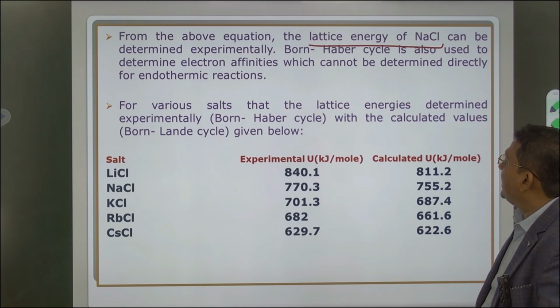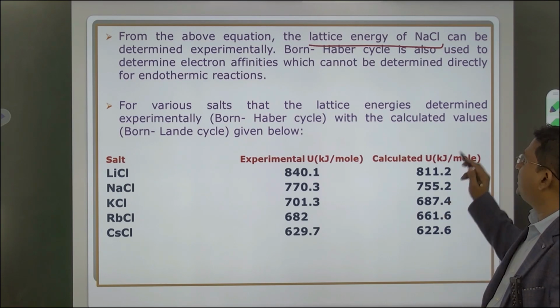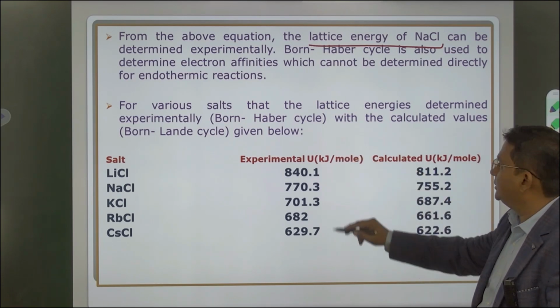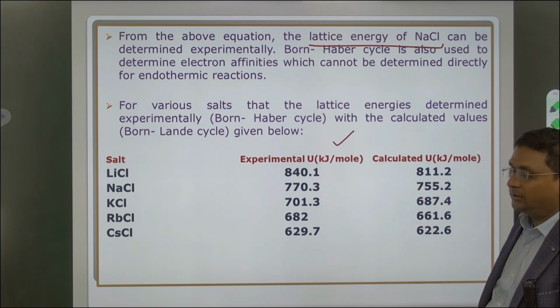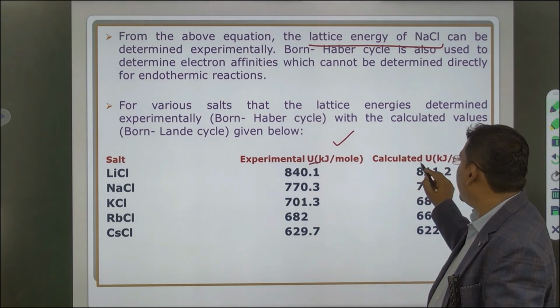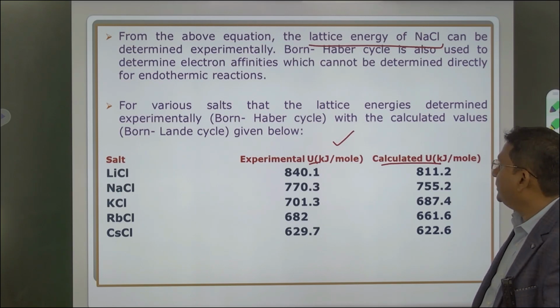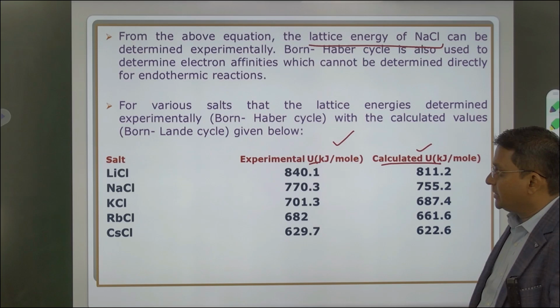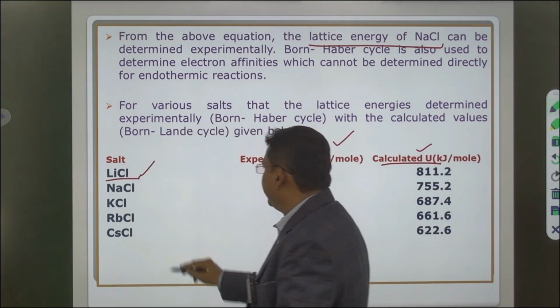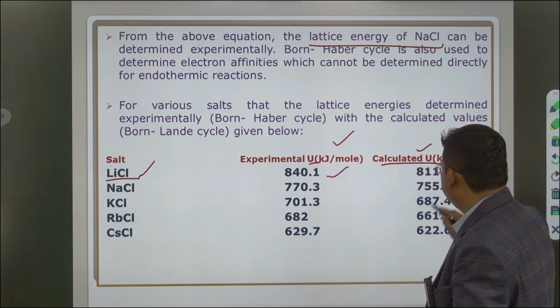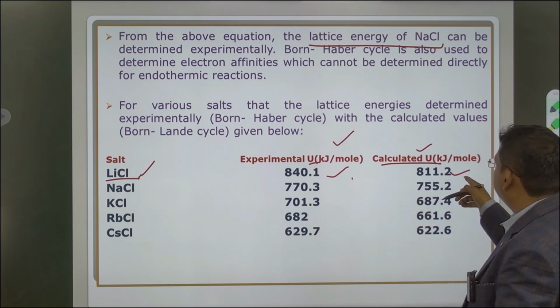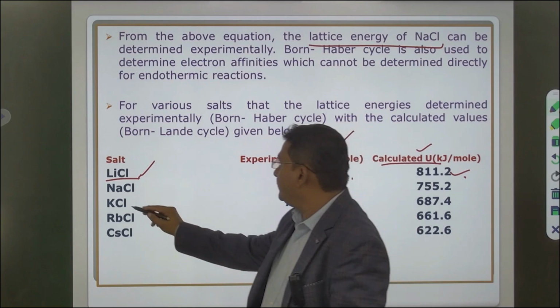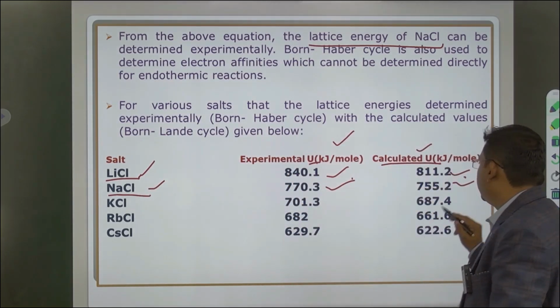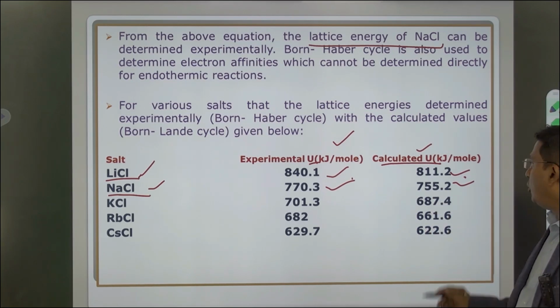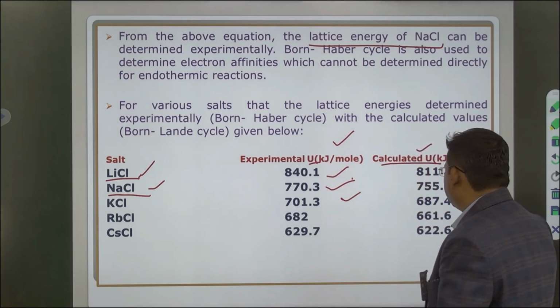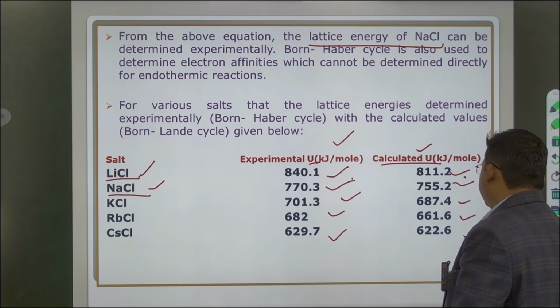For various salts, the lattice energy determined experimentally is compared with the value calculated from the Born-Lande cycle, given below. This is the experimental data of lattice energy, and this is the calculated data for the salts. See, lithium chloride: this is the experimental value and this is the calculated value. Like NaCl, we also find close values of experimental and calculated values, as we see here.